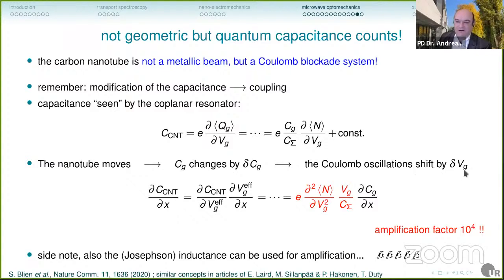And so if we are just at the right working point, we can influence the system much more by a small motion than just by the geometric change of the capacitance alone. We can calculate this effective capacitance, and we get an amplification factor compared to the change of geometric capacitance. If we pick the working point right, we end up with a 10 to the power of 4 here. And that's just the factor that has been missing.